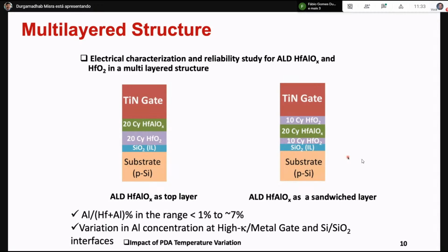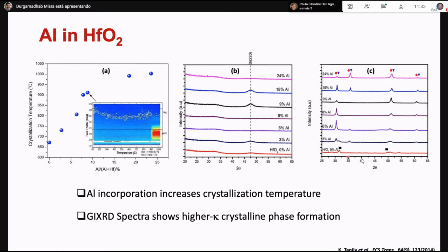That's because the aluminum was introduced because of the temperatures that you go through. The device goes through several temperatures before it's completed. The science behind that: if you add aluminum, the percentage changes the crystallization temperature. Hafnium oxide, which is amorphous, crystallizes around 650 to 700 degrees Celsius. Most processes are at very high temperature, around 900 to 1000 degrees. Sometimes you may have to go through the dopant activation process, and during that time the high-K dielectric can crystallize. So to avoid that, aluminum was introduced.